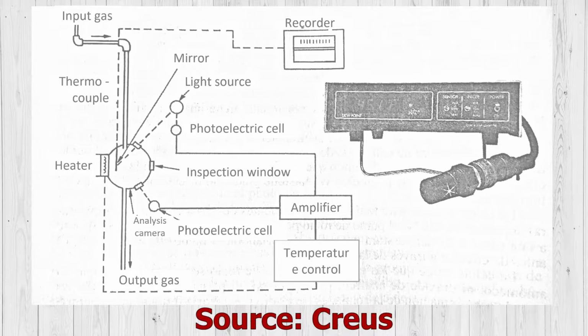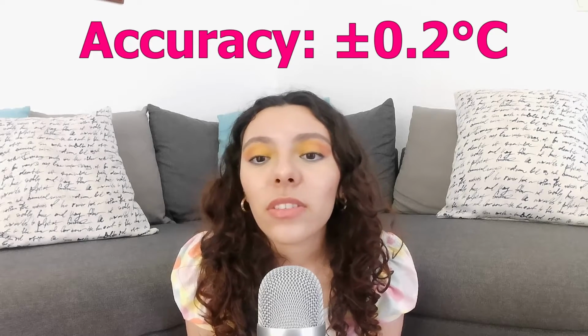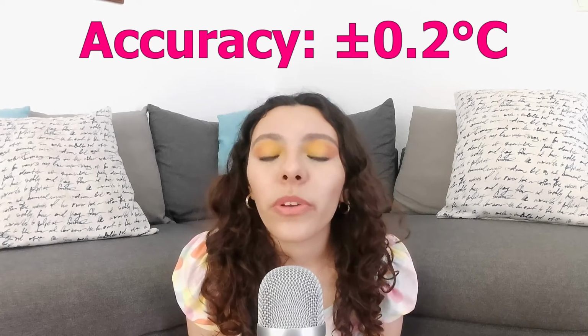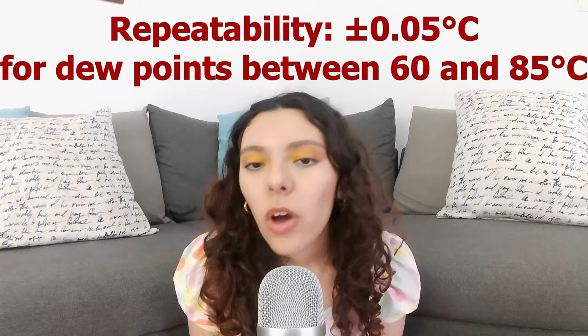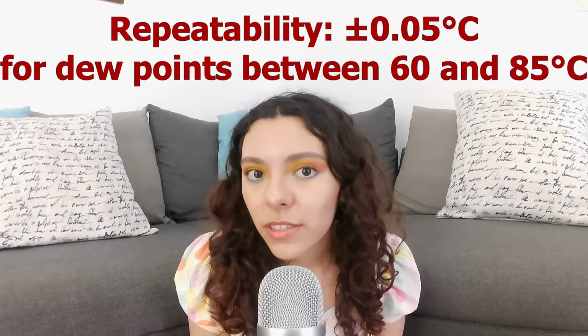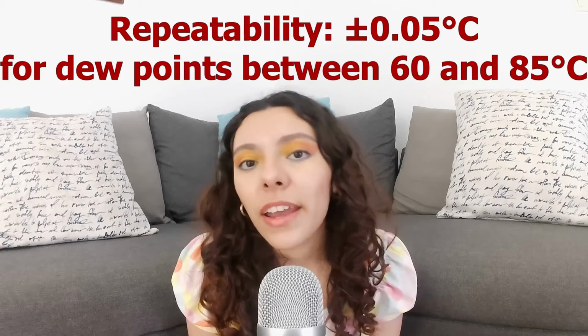The condensation system in a mirror consists of a chamber with a heating and cooling system that controls the temperature of the surface of a mirror located inside, and through which a current of gas circulates whose dew point must be determined. A photoelectric cell acts on the cooling or heating system to achieve constant fogging of the specular surface. The temperature of this surface indicates the dew point of the gas. The instrument has a total accuracy of ±0.2 Celsius and repeatability of ±0.05 Celsius for dew points between 60 and 85 Celsius.